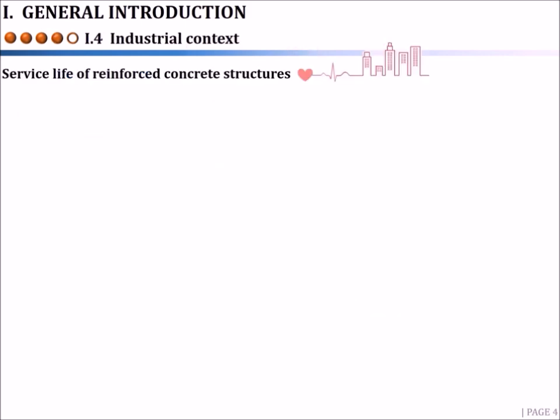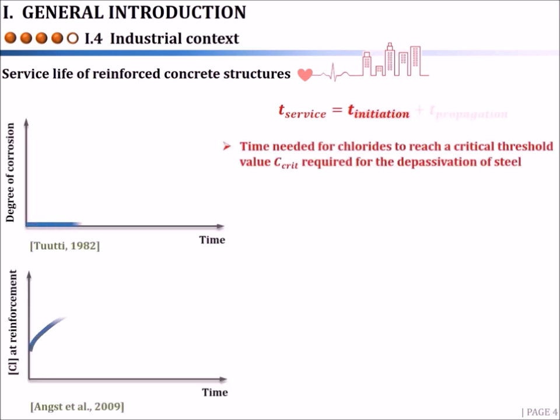Nowadays, the major concern for industrial companies is the duration of service life of reinforced concrete structures. According to Tuutti's model, the service life can be divided into an initiation stage and a propagation stage. The initiation phase is the time needed for chlorides to reach a critical chloride threshold value required for the depassivation of steel.